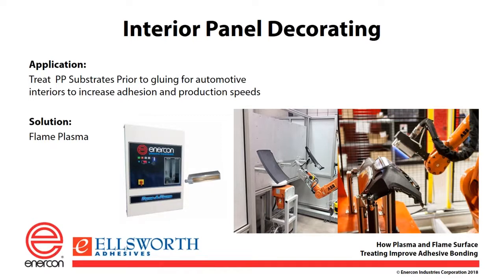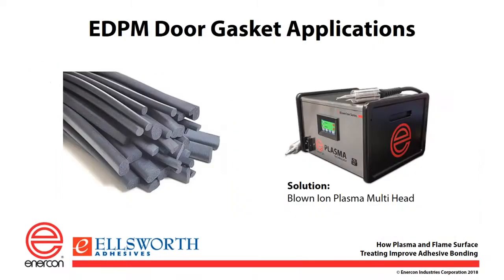The interior panels of your car, we mentioned the dashboard earlier, but all interior panels are generally a fiberglass or polypropylene of some sort, and you can treat that with either a blown ion or a flame, depending on the size of the part. Increase that surface energy right before the decorative portions of the car are put in there so that the interior looks nice. Again, flame plasma is a general application for this.